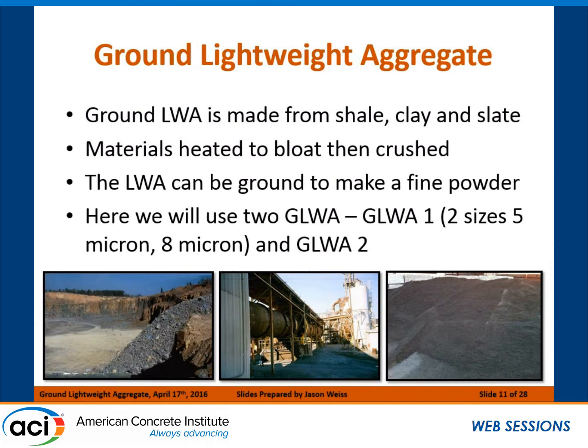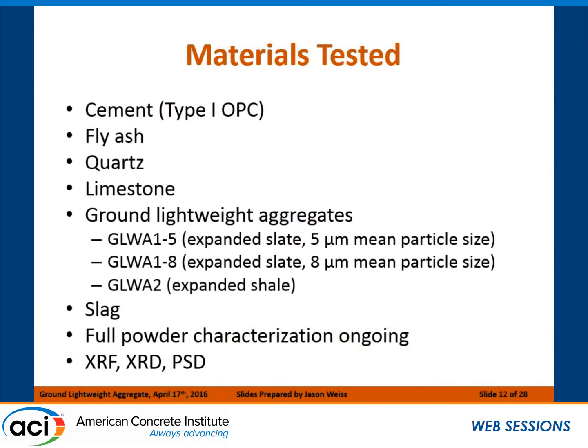Again, the ground lightweight aggregate here, it's going to be made from an expanded shale, slate, or clay. The material is heated to bloat it up, so the whole idea of making lightweight aggregates is you try to capture gas inside the material as it heats up, makes the material more lightweight, but then you end up with a lot of fine powder at the end of the day. And what you can't use for aggregates, the question is, can you use this as a ground supplementary cementitious material? So the whole idea here is we're going to look at an average 5 micron particle size and an average 8 micron particle size with two different lightweight aggregate chemistries.